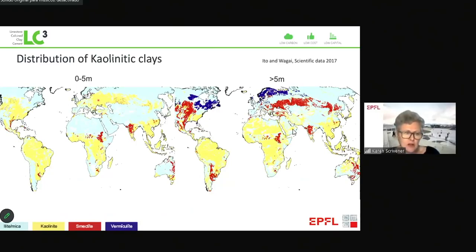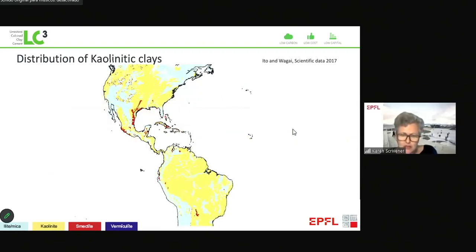So these maps show the main clay type in different areas. What we're looking for is the areas that have this kind of yellowy orange color, which is related to kaolinite as the main clay type. And you can see it's really abundant, particularly in those parts of the world where development is occurring most strongly, like in Africa, South America, Southeast Asia, India, etc. But we also have quite large deposits in the USA and even in Europe. And if we zoom in a little bit on the region where you are now, you can see all around here very nice clay deposits.